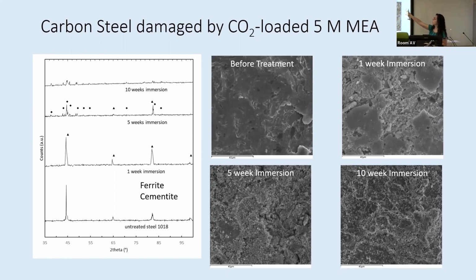So we're seeing an increase in the presence of that cementite, which indicates that the more labile iron ions have been removed from the surface. But in particular, that means we're making changes to the microstructure of this solid, which means that its stability, in terms of its ability to have the properties which somebody has purchased it for, no longer exists.